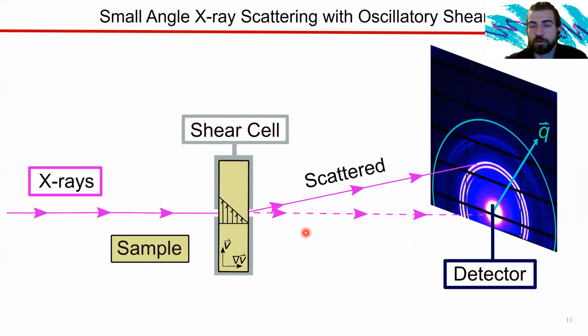So what we did is we took our samples to Argonne National Laboratory, to the Advanced Photon Source, and we put our samples into a shear cell where we can oscillate back and forth. And we're going to send X-rays down the gradient of shear, and they're going to scatter on this detector.